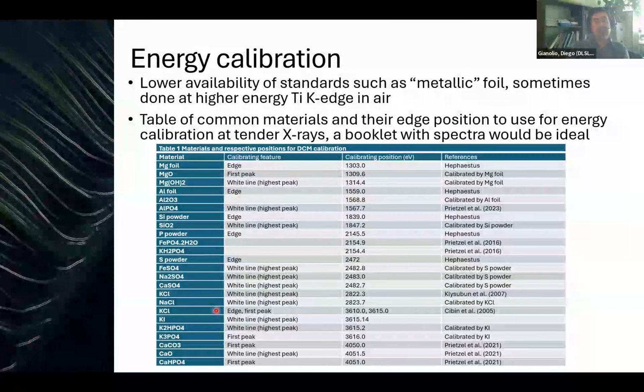There is a first draft of the table where some of the references are foils, so we take the reference from Hephaestus or from the X-ray data booklet, and some others are oxides or chlorides or different types of mixed oxides, where the position has been taken by doing a measurement of the foil and then immediately after the measurement of this material. So it has been calibrated to another energy and then measured. So we think this could be a starting point, with the hope of populating this table more and more, and also making the calibration more consistent across beamlines.